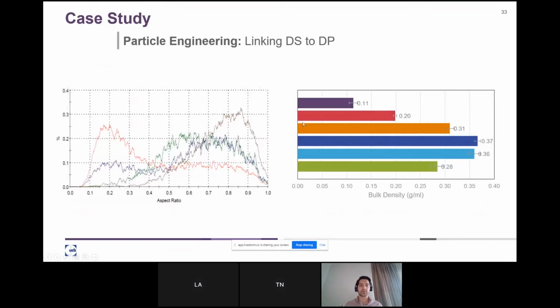And then this has a subsequent impact on the properties. Here we are showing the bulk density. You can see that for different shapes of the same crystal, we can have different properties. The higher this value of bulk density, the better it is for us. You can see that in one case it went from 0.1 to almost about 0.37.